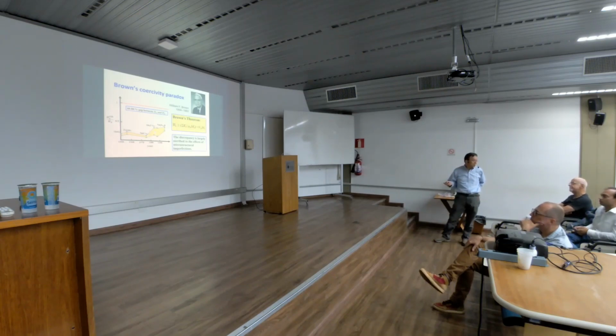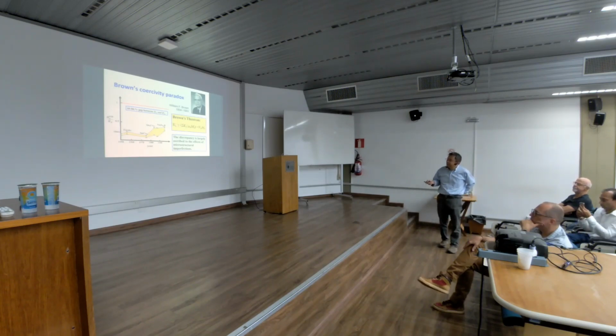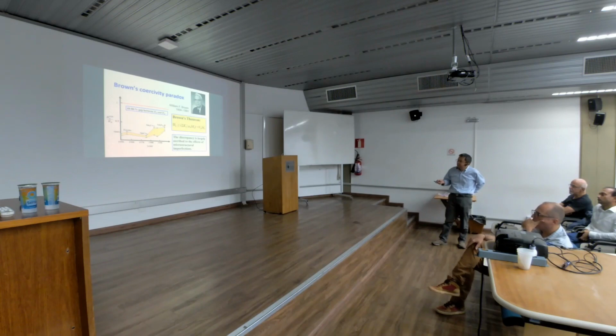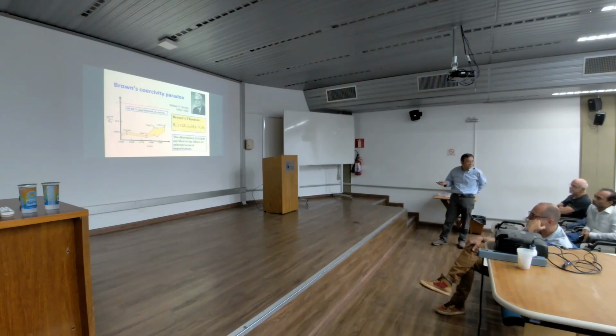It's quite some years ago. Even I did not exist at that time. Say coercivity should be large, or at least equal to this term minus this term. This term, if you are familiar with micromagnetism, is called the anisotropy field. This is a field, okay, you can calculate. This is an anisotropy constant. This is magnetization. Minus Dn is the demagnetizing factor.